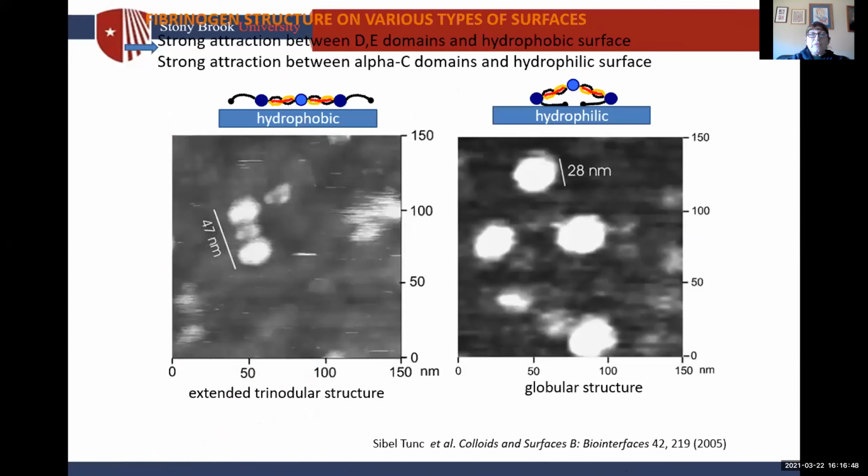So the fibrinogen molecule is very sensitive to the structure of surfaces. And what you're seeing here, this is older data back from 2005, or was it ours, from the literature. If the surface becomes hydrophobic, the interior of the fibrinogen molecule adsorbs, and it adsorbs flat with enough energy to mimic thrombin so that the fibrinopeptides are released and the fibrinogen molecule is now open.